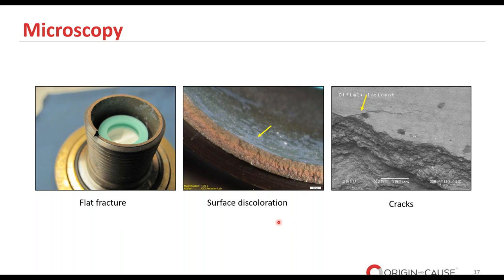Additionally, surface discoloration stands out. In the context of stress corrosion cracking, discoloration like this can hint at localized corrosive environments or specific chemical interactions that might be promoting crack propagation. And most importantly, the presence of microcracks, and this is an SEM image from the electron microscope. This is a strong indicator. SCC often starts as tiny, almost invisible cracks, which under the combined effect of stress and a corrosive environment can grow, leading to catastrophic failures. But taken together, these microscopy findings provide a compelling case for the potential involvement of stress corrosion cracking in this faucet's failure.